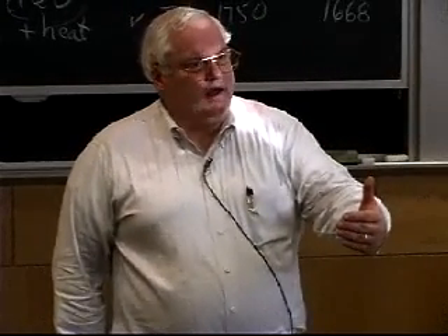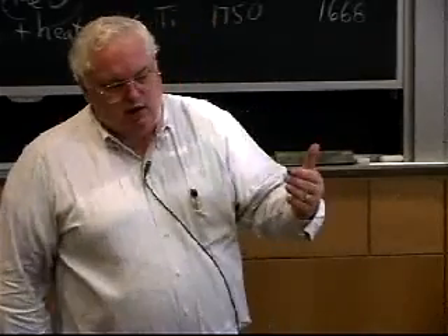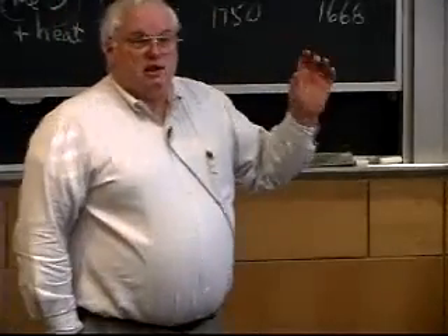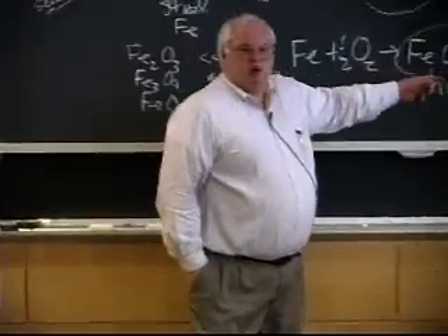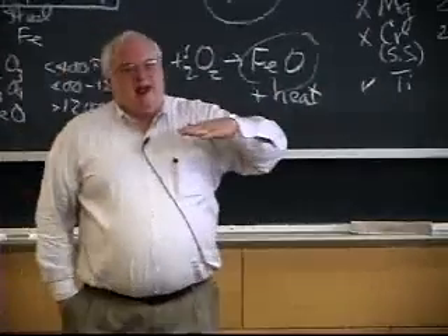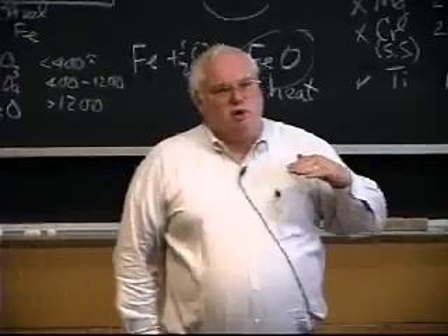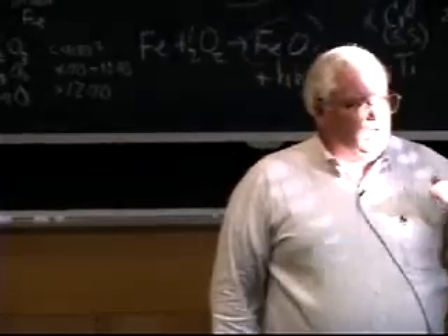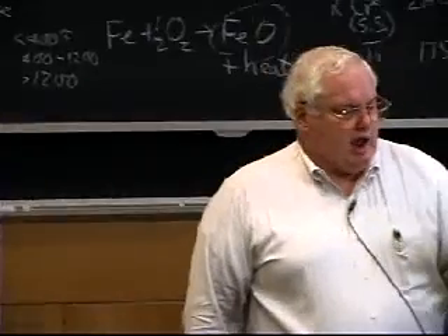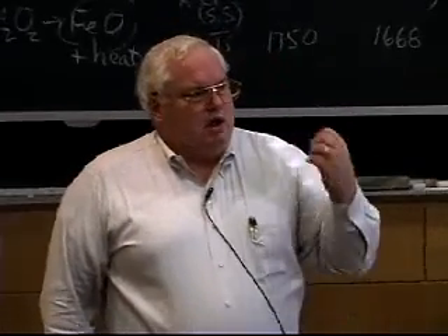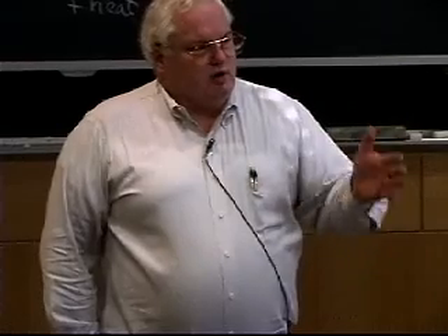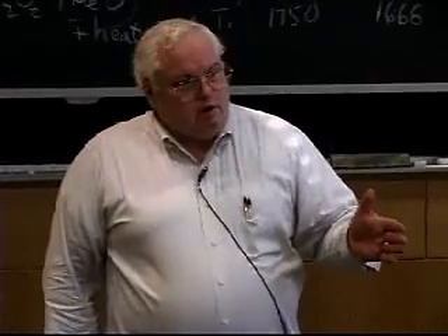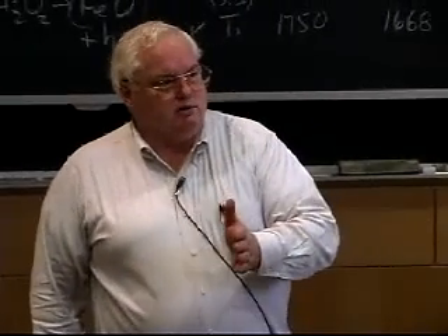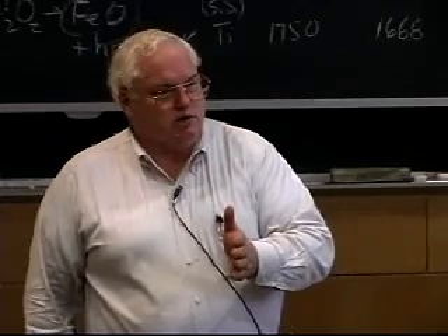Okay? And so, if I calculate a combustion intensity, it's the enthalpy of this reaction times the velocity at which the oxygen is coming to the surface, and I don't have to degrade it by 90 to 98% because of a boundary layer. I actually have the full heat intensity on the surface. So I go from 1,000 watts per square centimeter to 100,000, or close to 100,000 watts per square centimeter, as